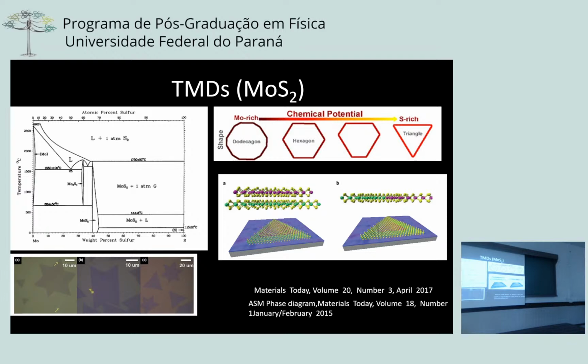First, you can change moly concentration or sulfur concentration, still it's MoS2, and you can get different size, different morphology, different defect concentration. So if you remember silicon, right, what you do? You do doping, phosphorus, boron and so on, right? Why you do that? To tune the band gap, right? Now the doping has to be very, very small, because if it crosses a certain range, it's going to be a different structure altogether. MoS2, you can have 5 atom% variation. What it means? 5 atom% is huge, right? In every 100 atoms, you can be 5 plus or 5 minus, still it is the same, right? You don't have to worry about precise composition, right?